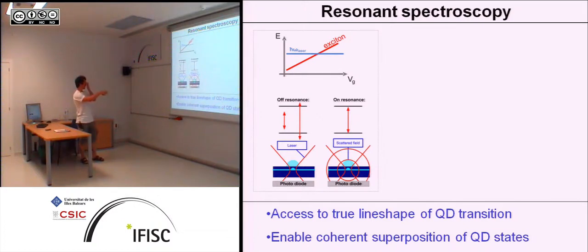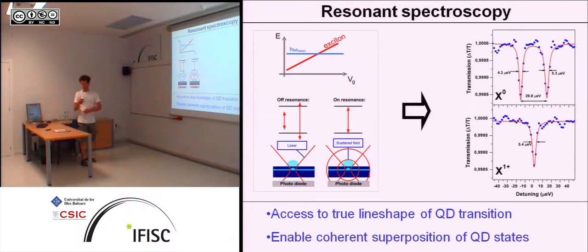And now we have these two situations. When you're off resonance, the laser will just transmit through the material, because besides the quantum dot, there are no states to excite inside the sample. But if the laser is on resonance, the exciton will start to oscillate in the electric field of the laser, and thereby it's basically an oscillating dipole. And then it scatters a fraction of this field, and what we now do is we detect the homodyne field of laser and oscillating quantum dot, and then you get something like this.